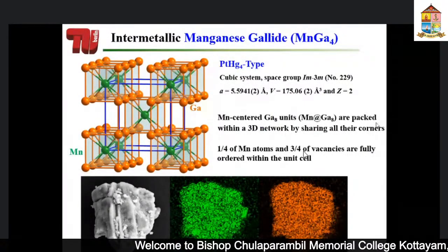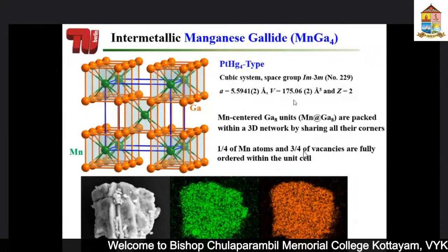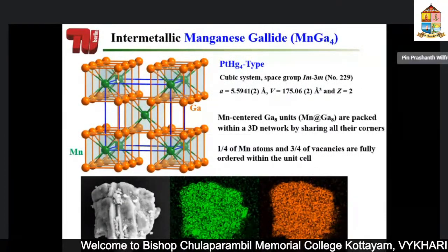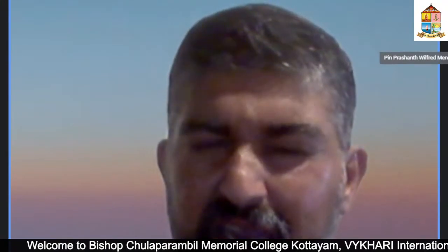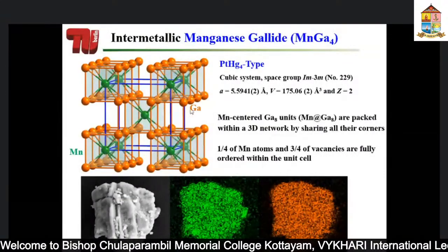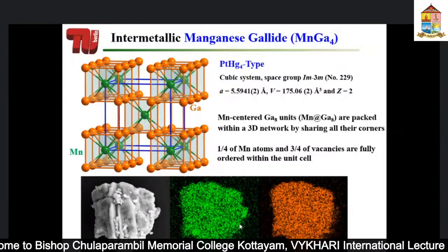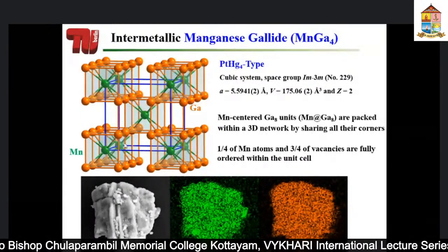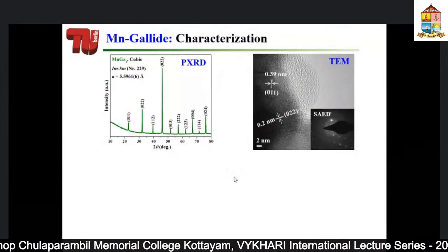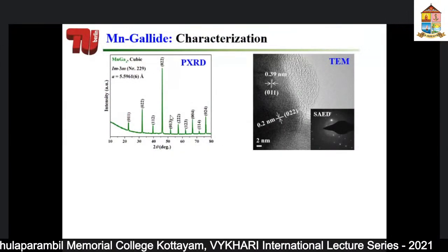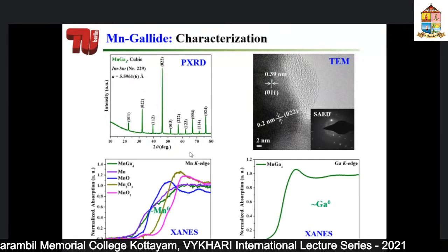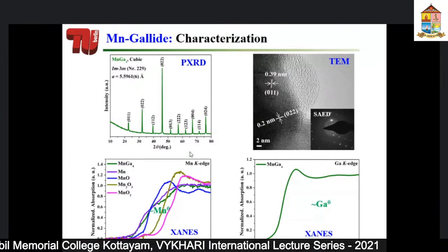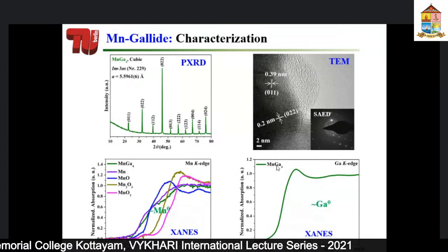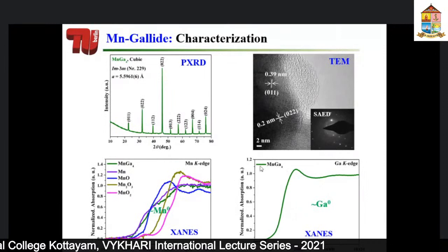data, but I would just show you that we also measured some manganese gallium structure, which also has beautiful structures crystallographically. It is very interesting, where each manganese is centered via 8 gallium units, that is gallium 8 units, and packed in a 3D network. This is a nice mapping picture. You could see the dispersion of both elements in the spectra. Again, the usual characterizations are XRD and TEM. This all means that what we made is a completely pure compound with an oxidation state close to 0 for manganese and 0 for gallium. So this is an intermetallic compound, so we expect the oxidation state to be close to 0.